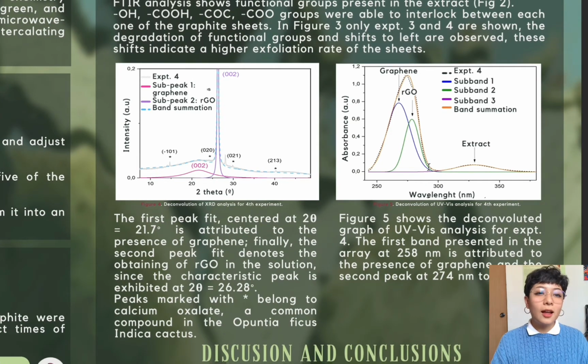As in XRD analysis, the ultraviolet visible spectra has a deconvolution treatment to observe the phases in the solution and their percentages. Figure 5 shows the deconvoluted graph of ultraviolet visible analysis for experiment number 4. The first peak present in the graph at 258 nanometers is attributed to the presence of graphene. The second peak at 274 nanometers to RGO, and a third band is visible at about 330 nanometers, belonging to the extract.